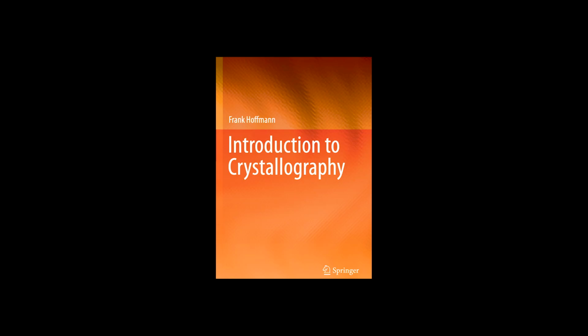So Penrose had found a mathematical way to create ordered but non-repeating patterns with forbidden symmetry, years before they were found in actual materials. Exactly. It was the theoretical proof that long-range aperiodic order compatible with five-fold symmetry was mathematically viable. Shechtman's discovery provided the physical realization. Okay, if quasicrystals defy the normal 3D lattice rules and the 230 space groups, how do crystallographers actually describe their complex atomic structures today? They have to use a more abstract mathematical framework. They employ the concept of higher dimensional crystallography. Higher dimensions, like 4D or 5D space. Even higher, typically 5D or 6D space.